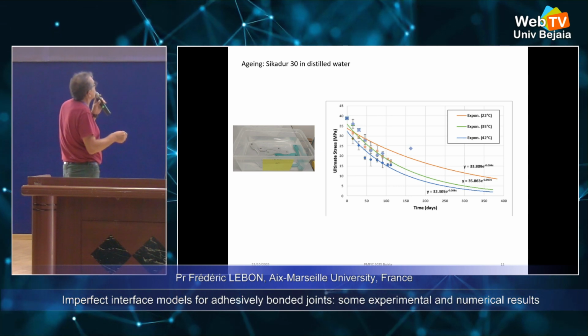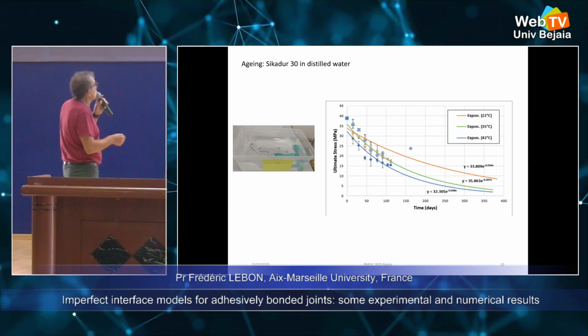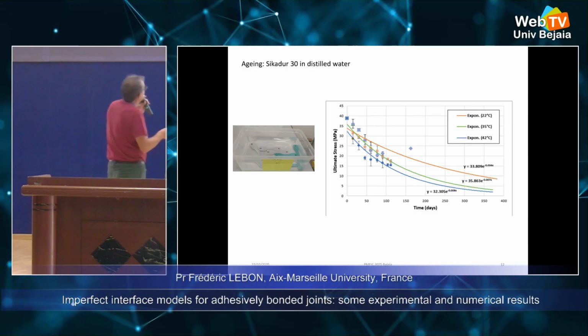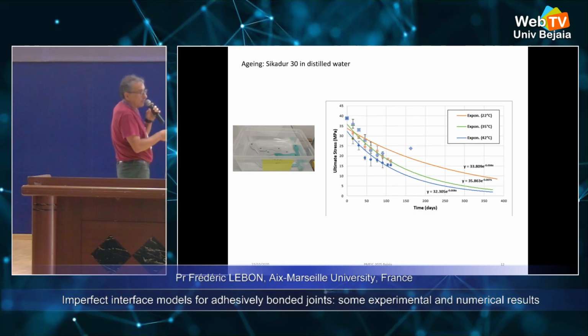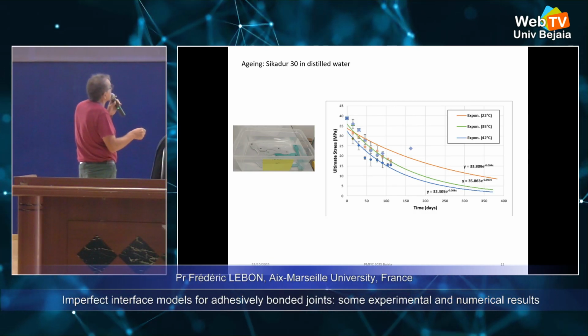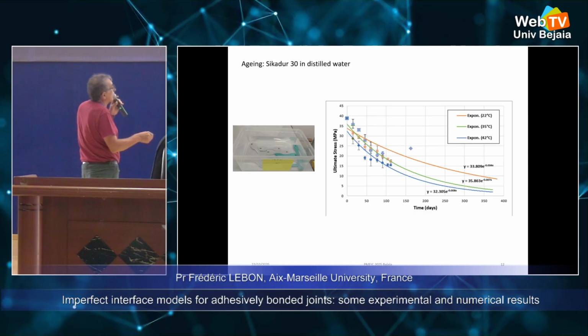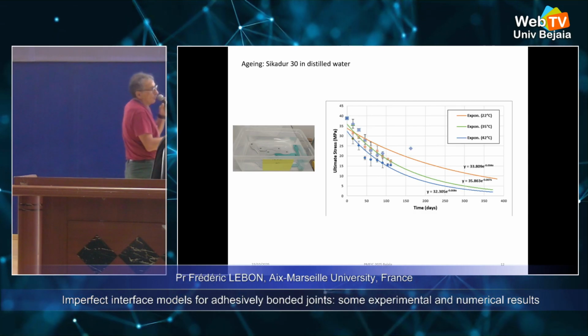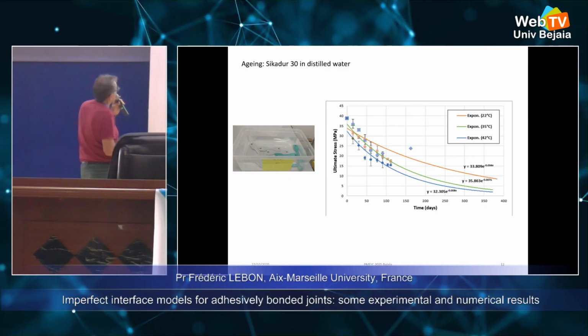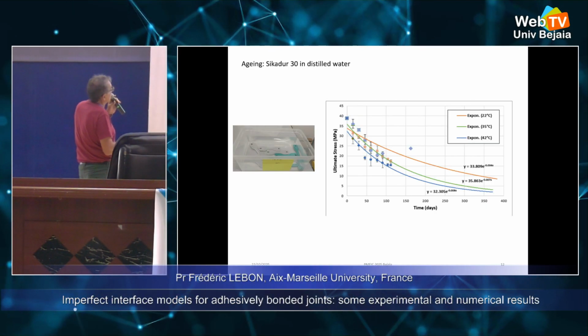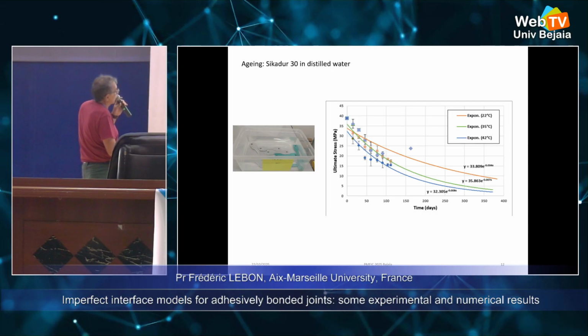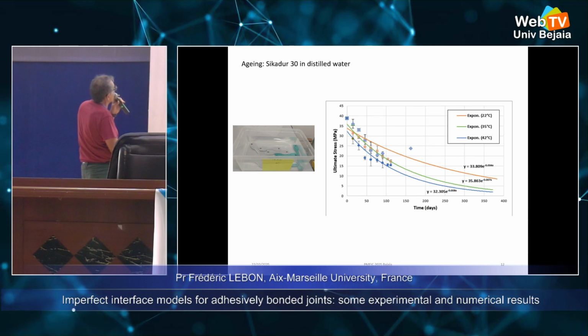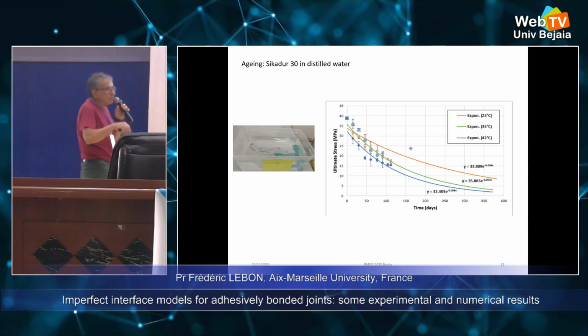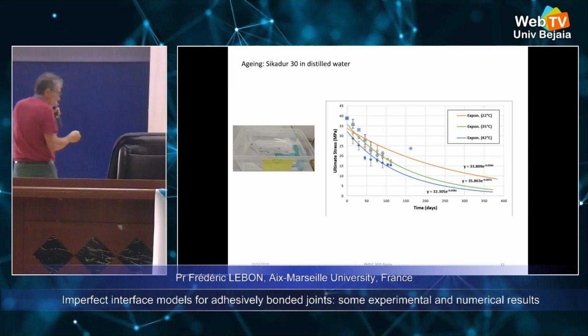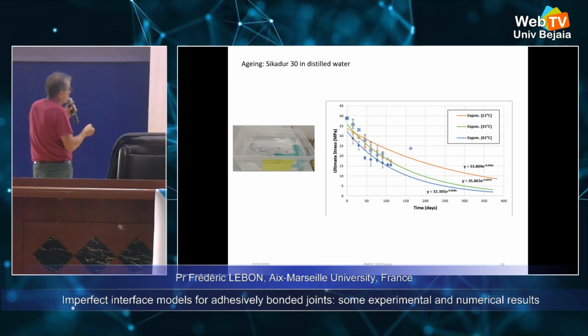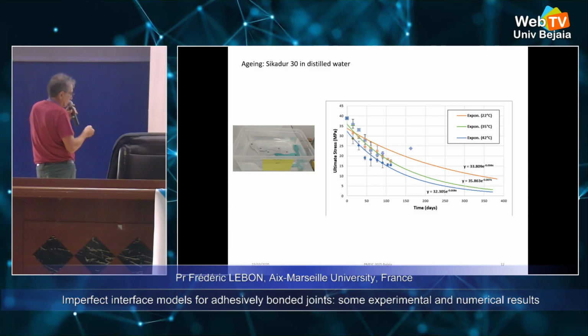For example, here there is an ultimate stress. So we use this kind of structures, and we have a tensile test, and we can try to obtain, for example, depending on the temperature, we have 3 kinds of temperature for this Sikadur 30 in distilled water. And we can observe that after, I don't know, 1 year, we have a figure like this. So we have a decrease which is quite exponential of the ultimate stress. So the same for the rigidity of the structure.